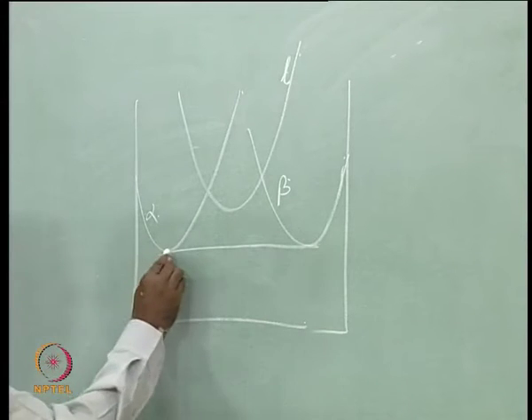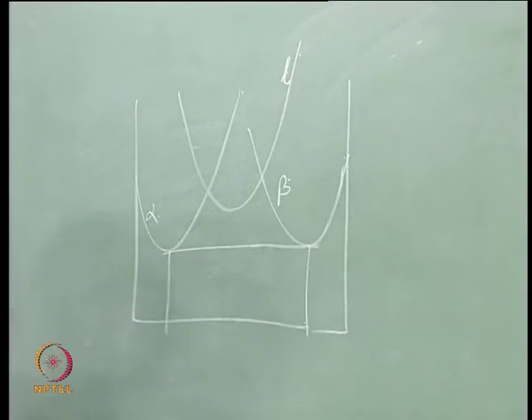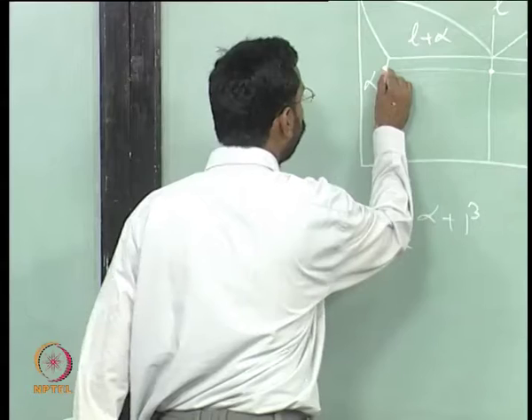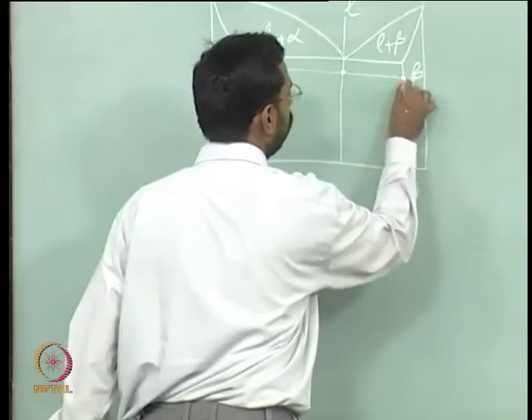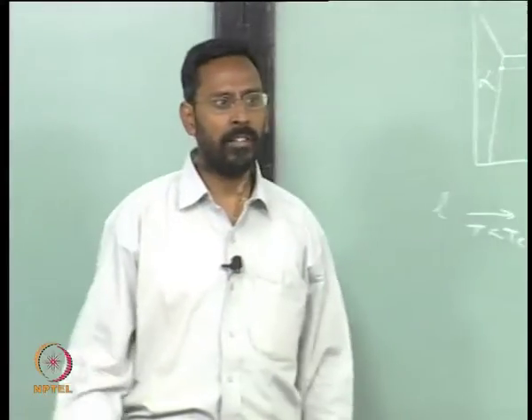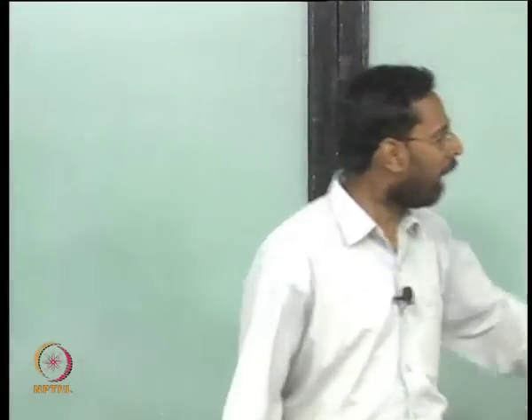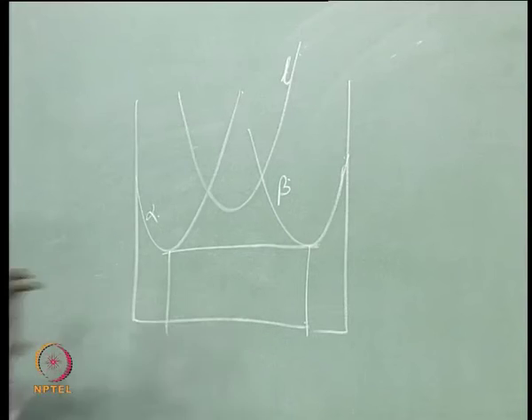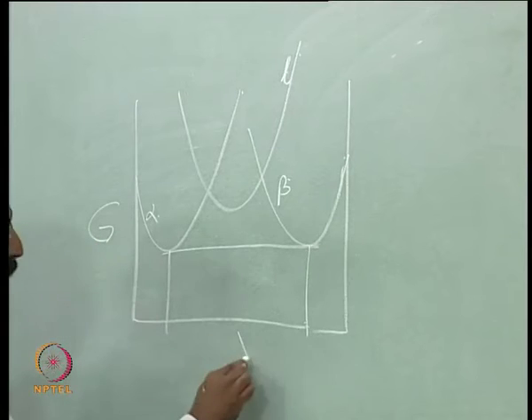And these two compositions where you have the common tangent of alpha and beta should correspond to these two compositions in our phase diagram, am I right? Because there has to be a 1:1 correspondence between the free energy composition diagram and the phase diagram. This is the G-X diagram, the free energy composition diagram.